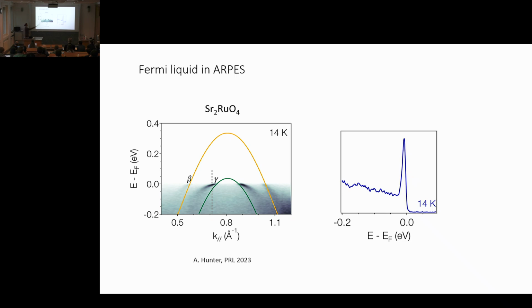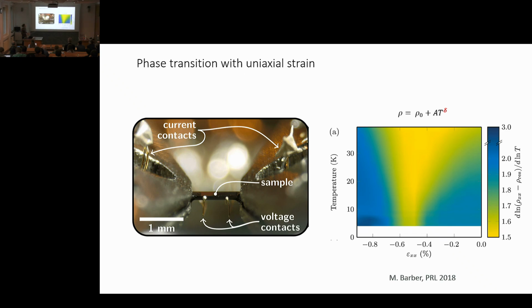So I have the non-interacting bands as single lines here. You can see that the quasi-particle bands are a bit flatter than our non-interacting bands, meaning they have a higher mass. You can also see that at the Fermi edge, they're fairly sharp. And then if you go lower in energy, they get wider and wider. Let's move on from Fermi liquid theory.